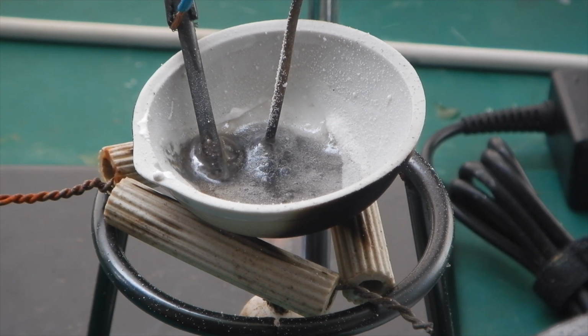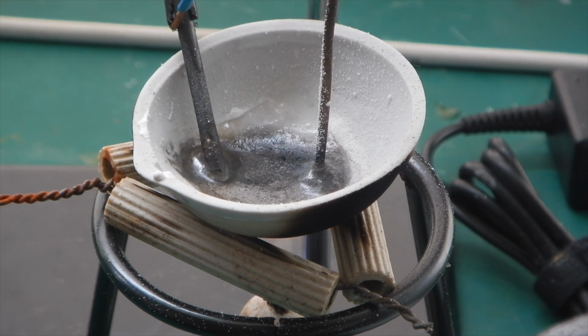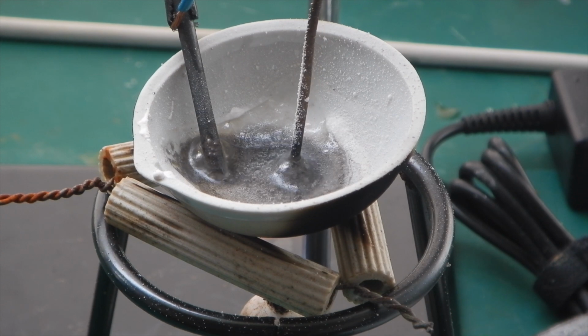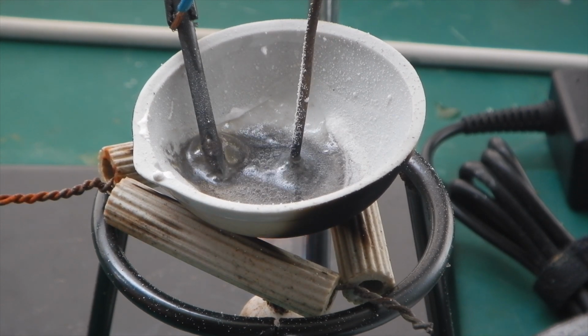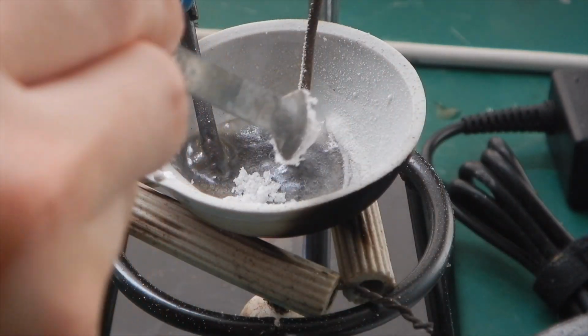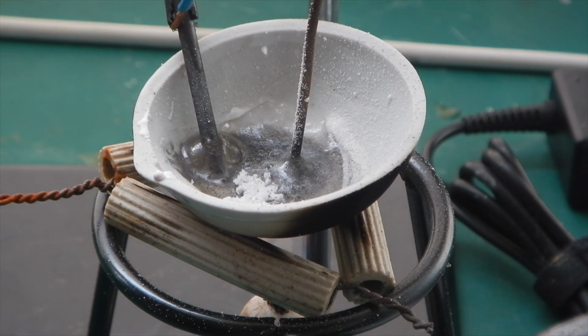After about 5 minutes, the mixture seems to grow a lot thicker. A lot of bubbles formed on the surface of the melt and stayed there. You can still see me feeding more salt into the cell. The extra salt cannot fully melt at this temperature, and I think this is what caused the mixture to thicken. A minute later, the extra salt seems to have melted, and the electrolysis proceeded on.